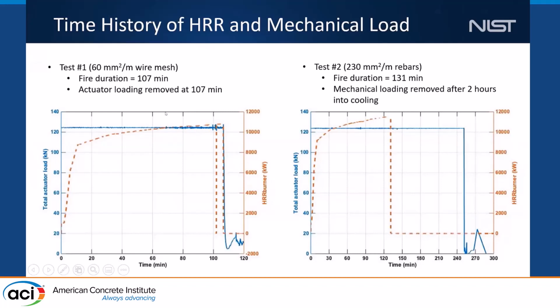Fire experiments are typically conducted such that we apply the mechanical loading at ambient temperature, which is maintained constant throughout the fire exposure. So basically, this slide shows the time history of the burner heat release rate, which characterizes the fire intensity, and the total actuator loads. In test number 1, the fire duration was 107 minutes, and then we actually had to remove the fire and the mechanical loading at the same time, because we saw that a huge center crack had developed in the middle of the test bay. In test number 2, the fire duration was 131 minutes, but the mechanical loading was continued over a 2-hour cooling period.